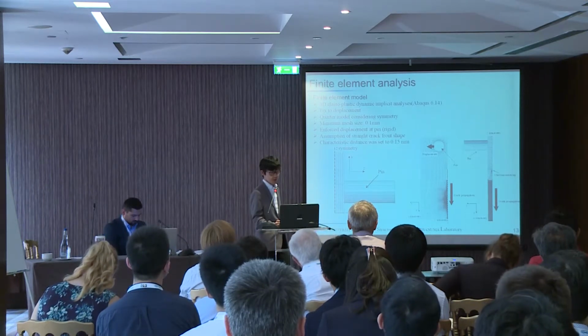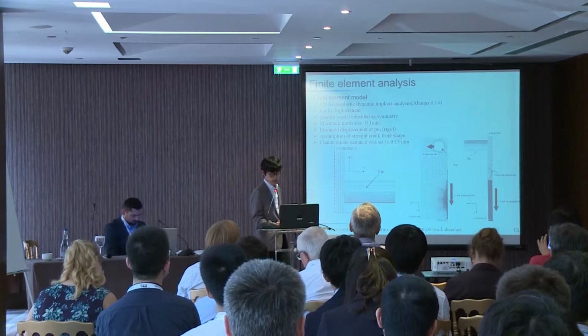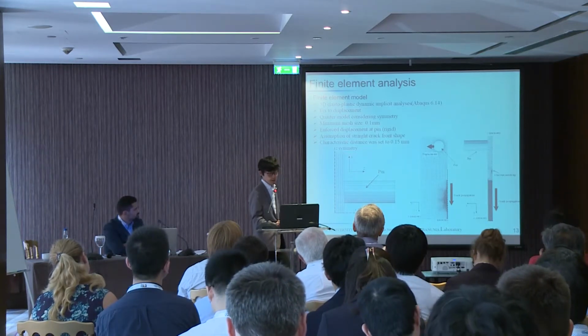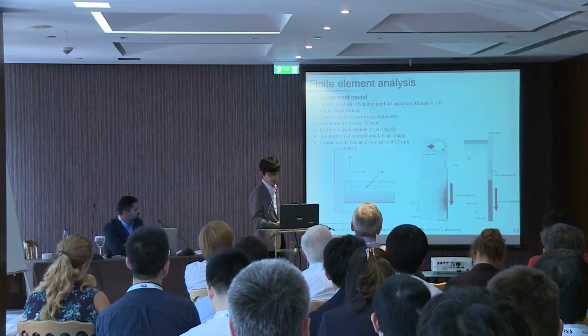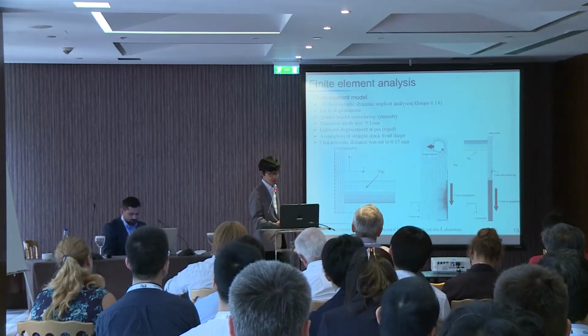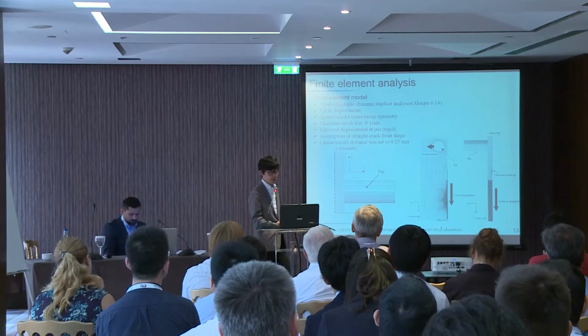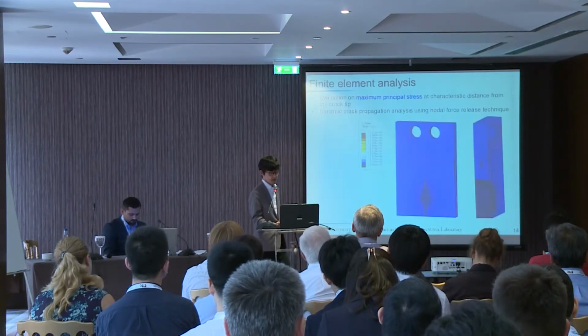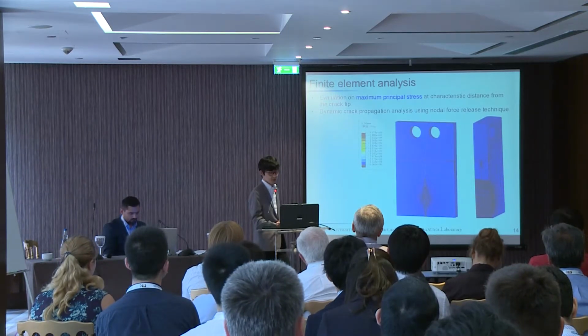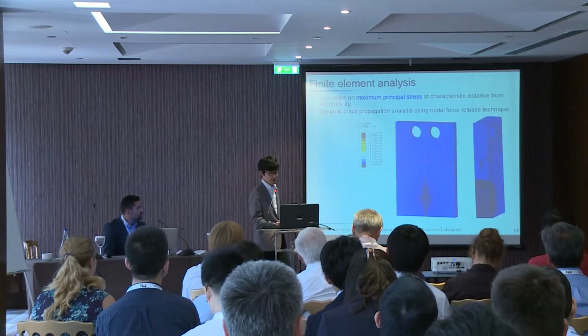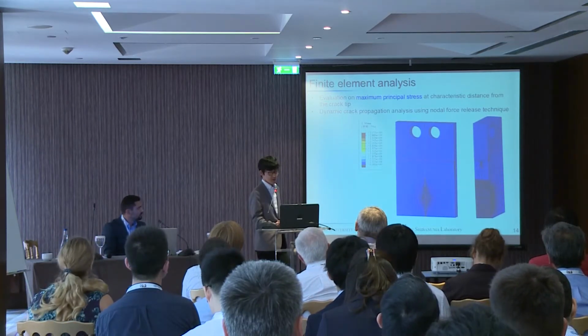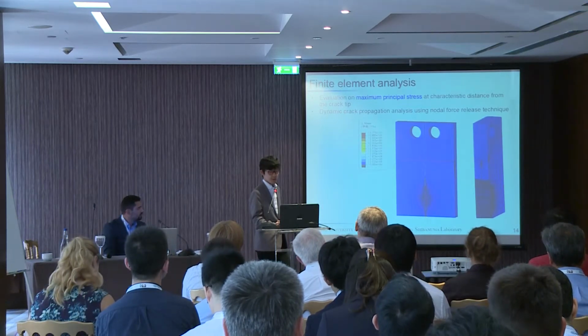After we obtained experimental results, we conducted finite element analysis. We carried out 3D elastoplastic dynamic implicit analysis using Abaqus 6.14. And in this model, we considered quarter model symmetry and crack front shape straight. And minimum mesh size is 0.1 millimeter, and characteristic distance was set to 0.15 millimeter. We conducted dynamic crack propagation analysis using nodal force release technique and evaluated maximum principal stress at characteristic distance from the crack tip.